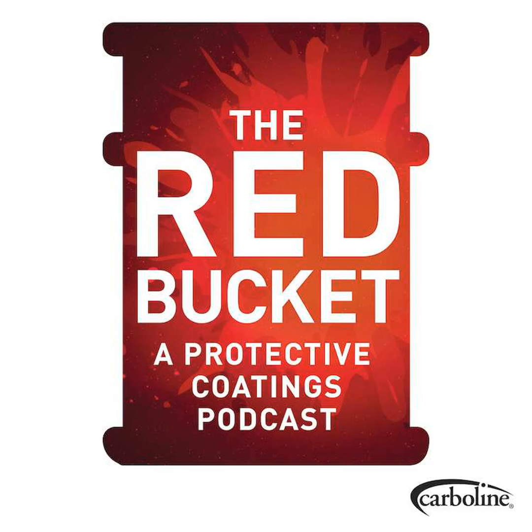When you go to thermal spray metalizing, instead of a big bath with the zinc in more of an acidic solution, you actually utilize a spray gun. I've had some people say you could almost compare it to an arc welder, but you're using really high heat, flame almost, to take that zinc and make it molten, and it sprays onto the steel. What's a little different here is that the steel has not been treated. It hasn't been, quote, pickled like you would see in a galvanizing process. So you're really just laying zinc down on the steel. What we have to do in thermal spray metalizing is use blasting to get a very deep angular profile so that we have a mechanical bond between the zinc and the steel.